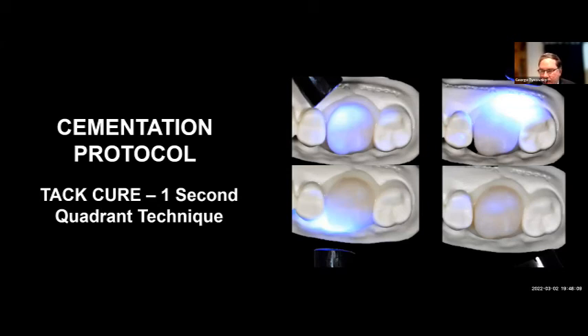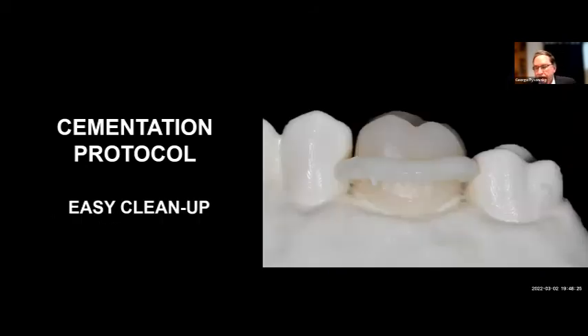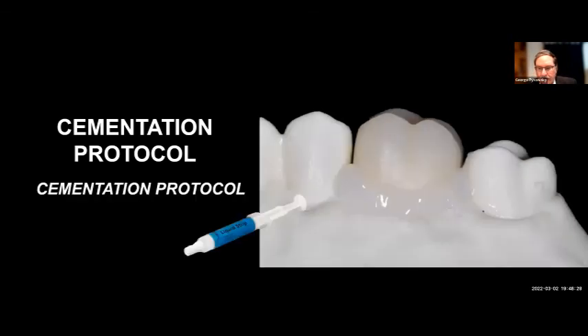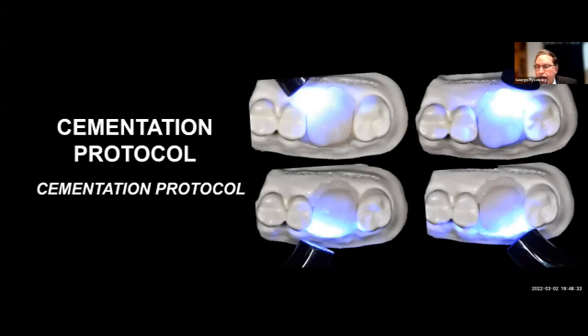Very popular today. Again, it's an intermediate step. I wouldn't do it on partial coverage or on thin preps, but if you have a decent retentive preparation, full crown, it's certainly a very viable technique because it gives you the strength and the flexibility and the ease of use of using these types of restorations. So again, easy cleanup, carving off the excess, and then basically final cementation, curing it fully to make sure we have full polymerization and completion of the restoration.